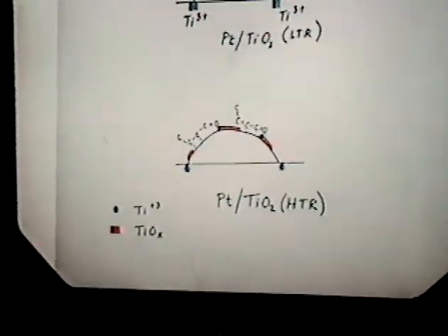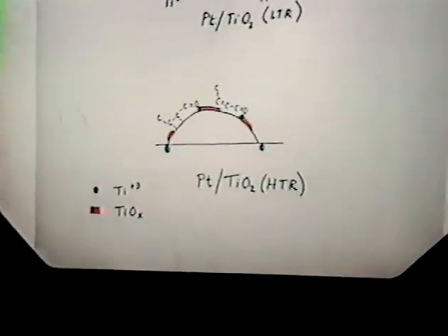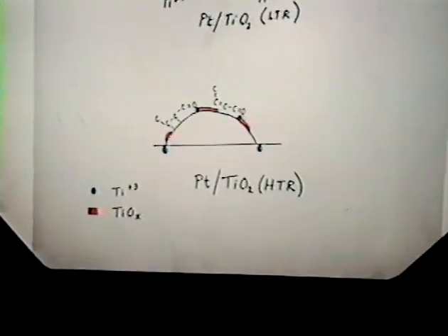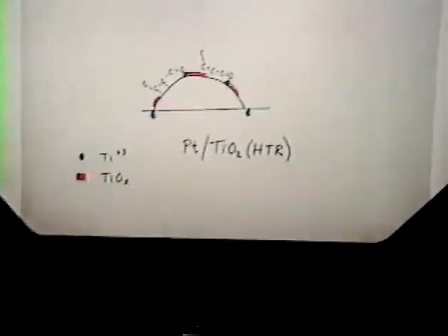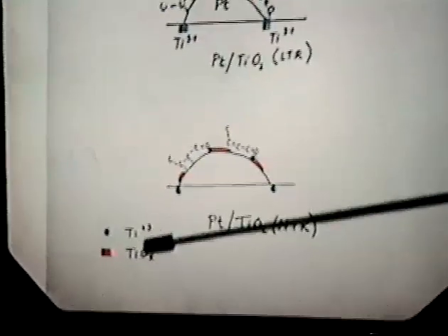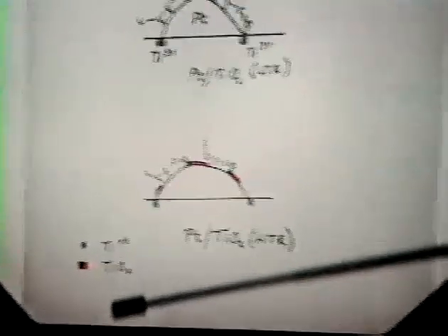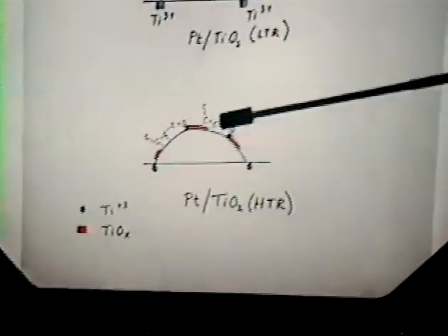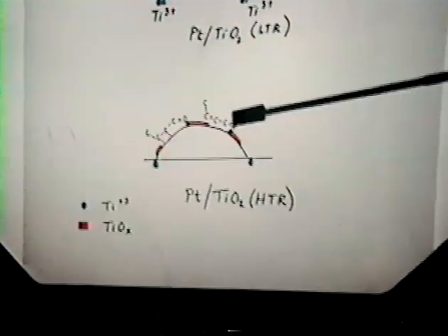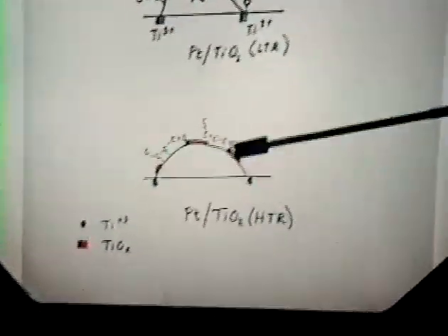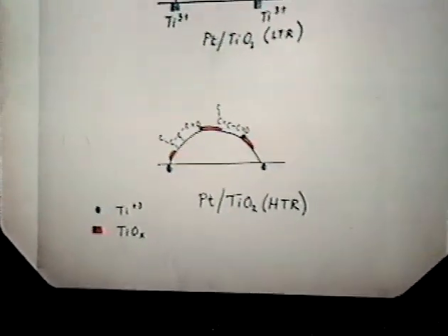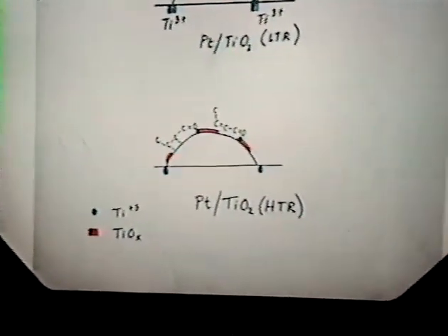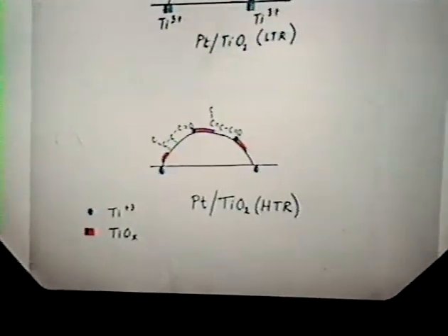After the high temperature reduction, as was pointed out, one major aspect of the titania catalyst systems is the migration of this TiOx species across the metal surface. So we enhance the interfacial region, the interfacial surface region between the metal and the titanium oxide. We suspect in these cases, we know that we have Ti3+ and perhaps even Ti2+ cations. We are proposing that these are probably the ones interacting with the carbonyl bond to enhance its selectivity to crotyl alcohol.